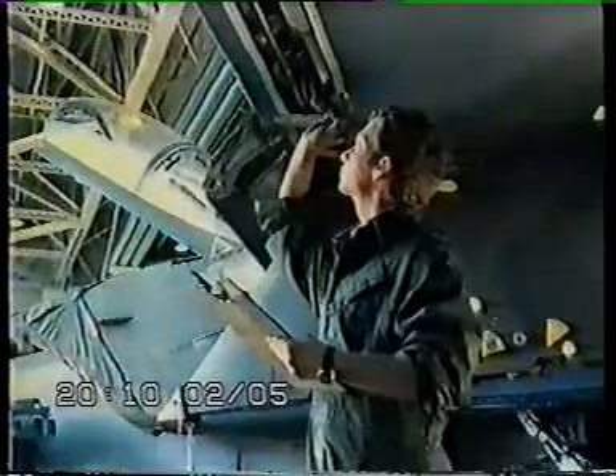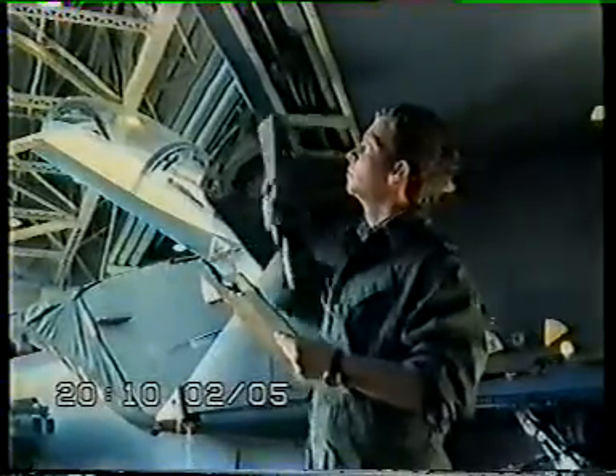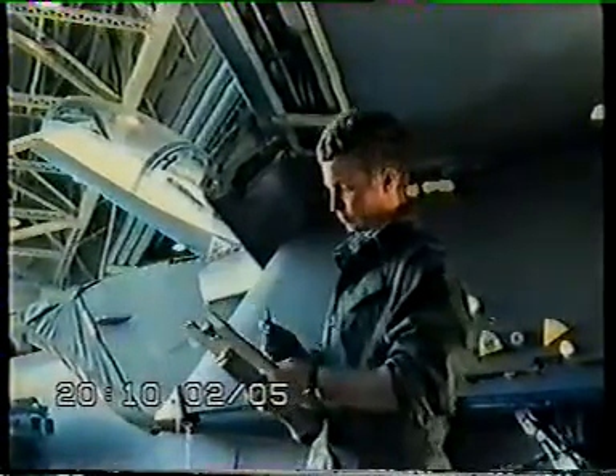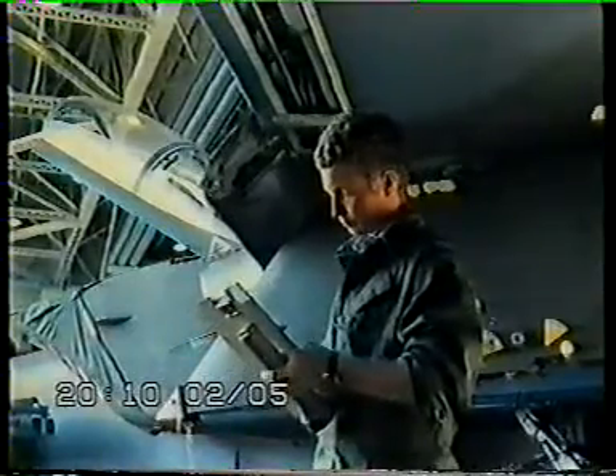By contrast, critical crack lengths for safe life structures may be quite small, only tenths of an inch. And once started, a crack may grow to this size quite rapidly. Whatever the design philosophy originally used, examination for cracks is a vital part of maintaining airworthiness. The correct frequency of inspections must be observed.